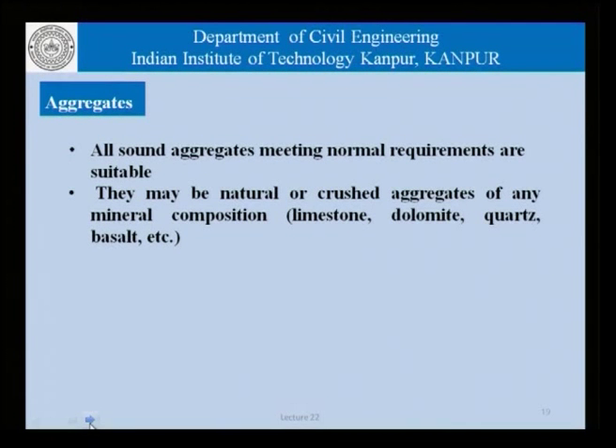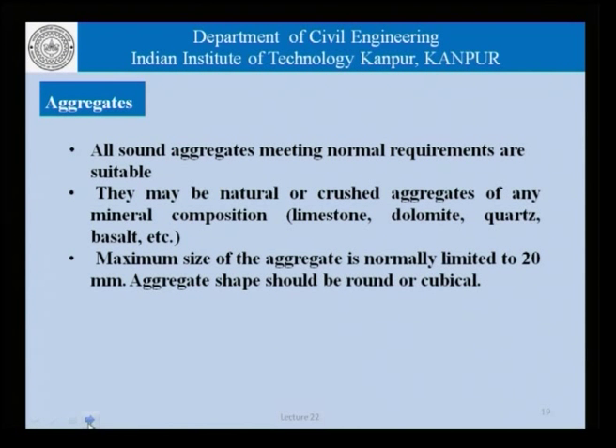These aggregates could be natural or crushed aggregates of any mineral composition, limestone, dolomite, quartz, basalt, whatever, except that the usual rules as far as alkali aggregate reaction will apply. We do not want to use reactive aggregates. As far as the maximum size of the aggregate is concerned, that is normally limited to about 20 mm. Aggregate shape should be round or cubical. Now, this is something which we need to be a little careful about as far as its use in self-compacting concrete is concerned, because